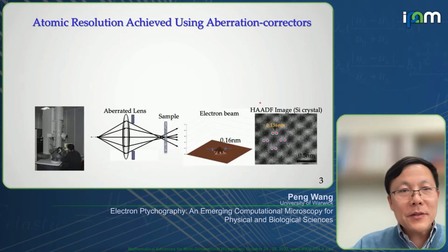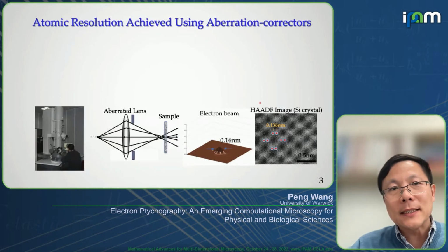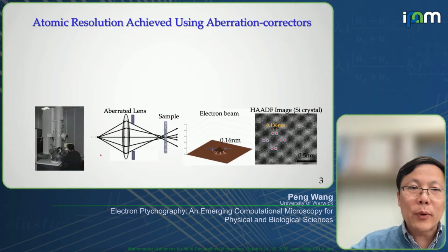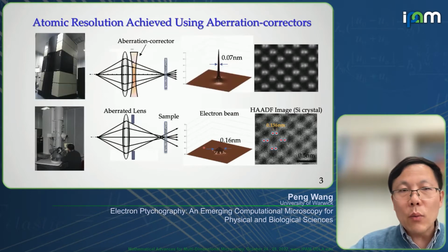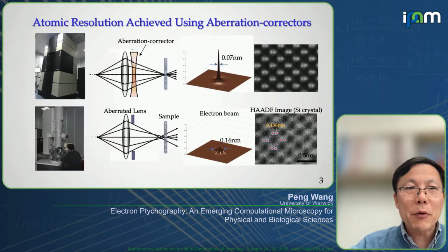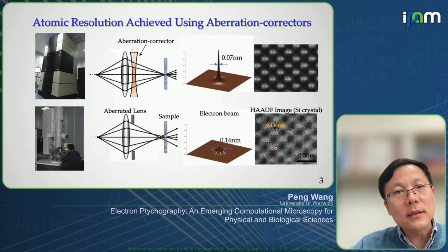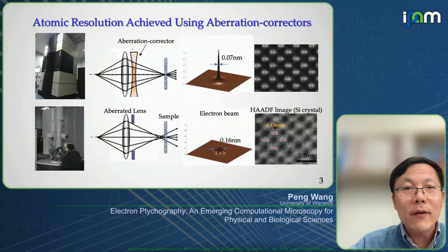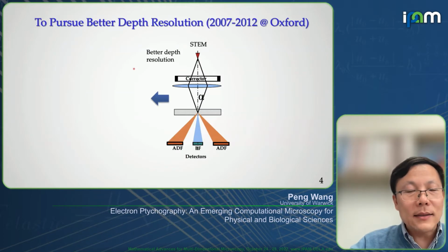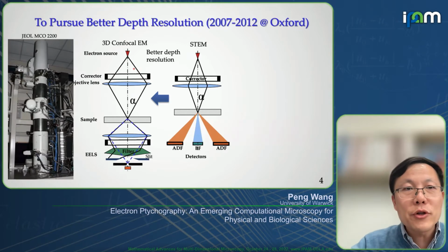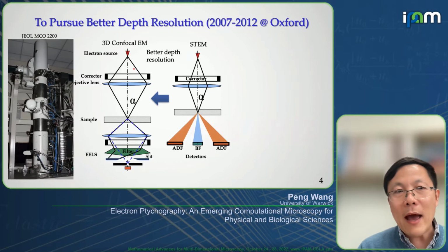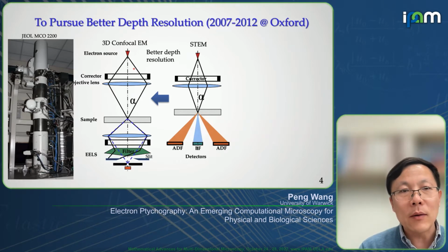Why do we like to do ptychography? The original aim is because previously the lens has aberration in it, so the resolution is roughly about 0.1 nanometer. But in the last decade, we have developed the aberration corrector, which allows the resolution all the way down to 0.05 nanometer in the XY direction, and this is all developed using hardware. In order to push the third direction, the depth resolution, we have put two double aberration correctors in one microscope, a confocal electron microscope mode.